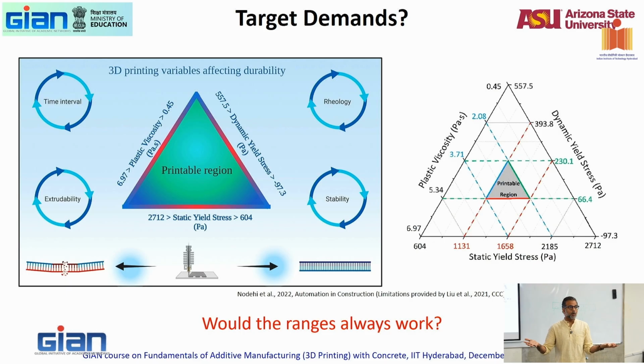None of us can say what you should change without seeing the mix and without being able to go to the field and actually see what is happening. And once you see it, you might say, okay, it is extruding, it is building 4 layers. I need to build to 8 layers. What do I need? Maybe I need to change my sand volume fraction from 0.45 to 0.55. Or I need to change my water cement ratio from X to this. It's extruding so well, I don't need to extrude it so well. Maybe I can reduce the amount of admixtures. Correct? All of those are decisions that an engineer makes in the field.